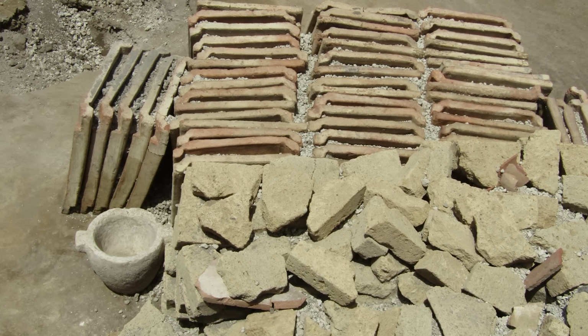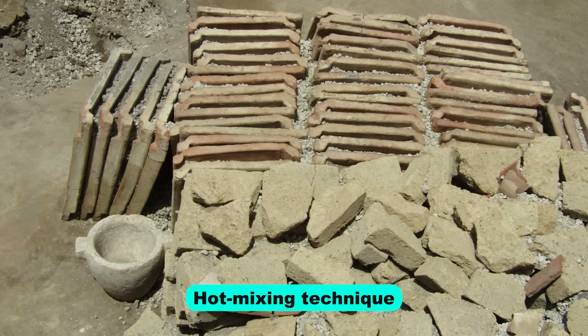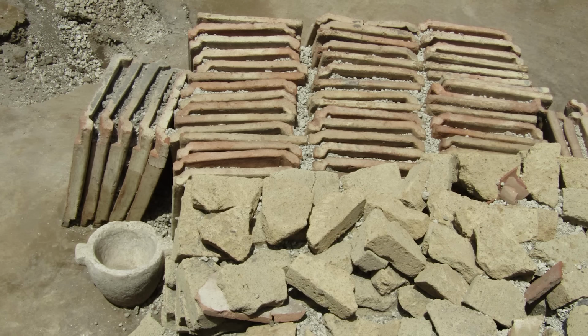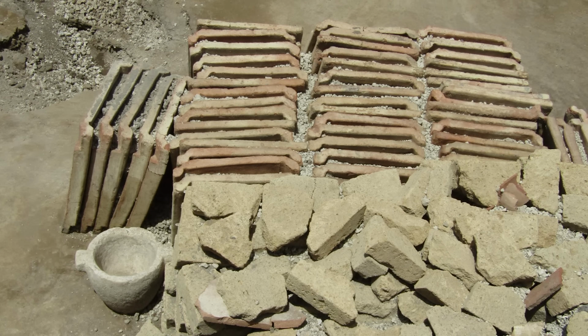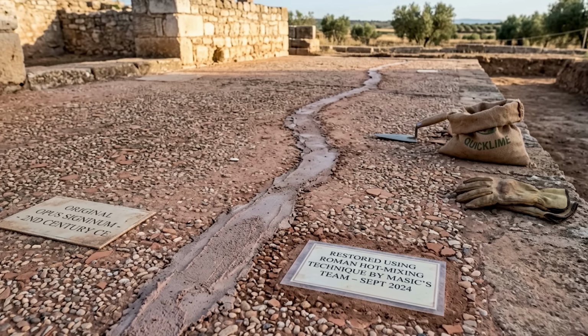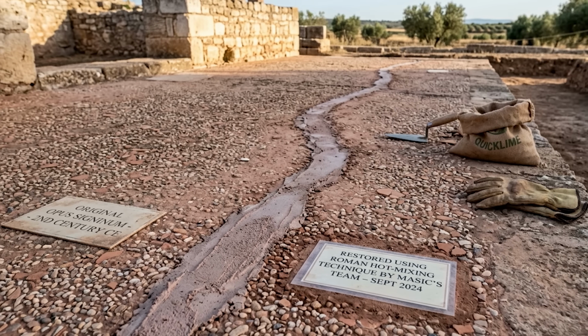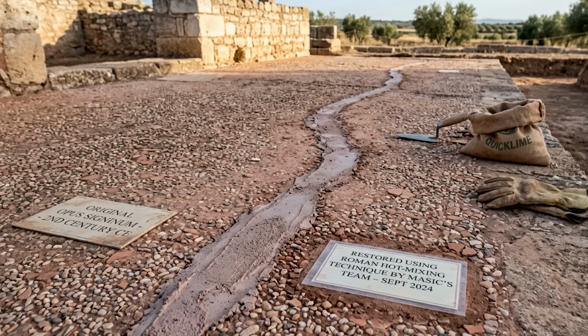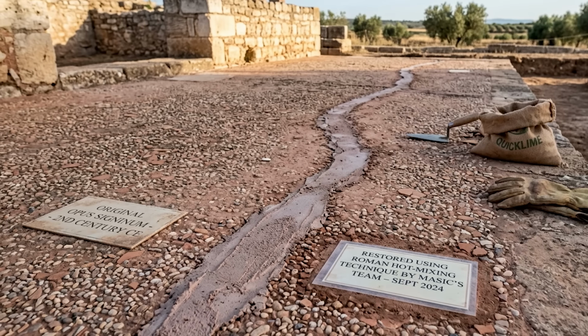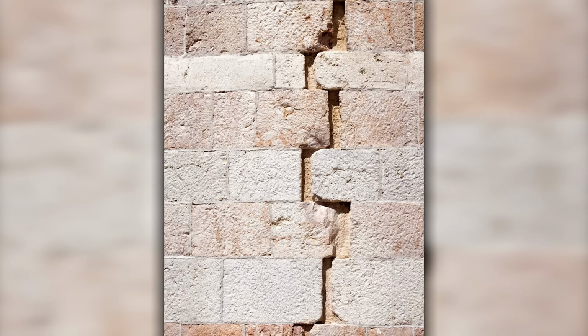Masick's team cast a Roman-style sample using the hot mixing technique, cracked it under load, and dripped water through the crack. 2 weeks later, the crack was sealed. The matching samples mixed with the modern slaked lime recipe stayed cracked. The mechanism is almost embarrassingly simple.